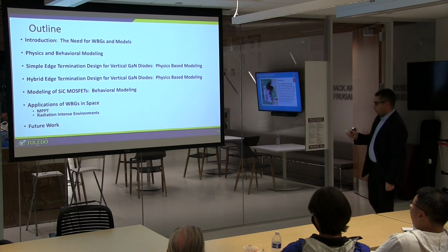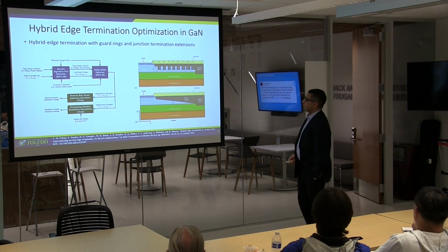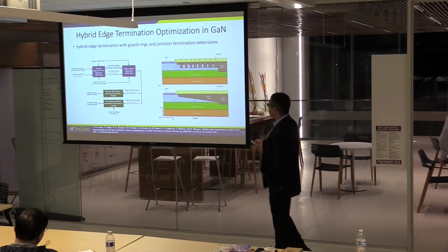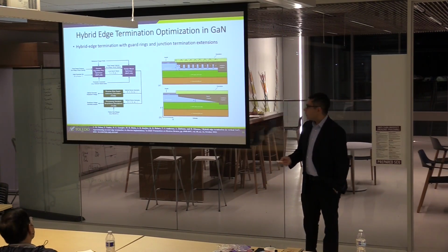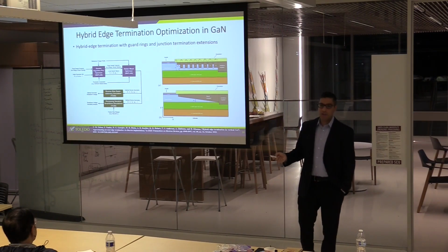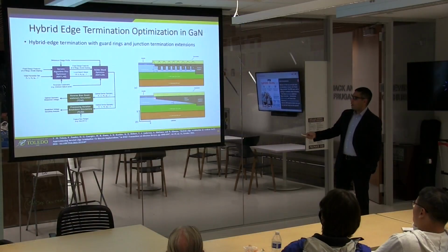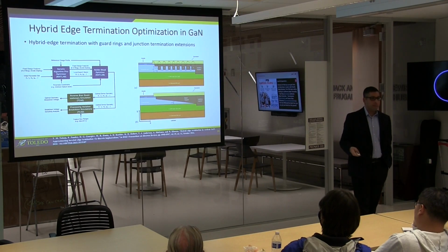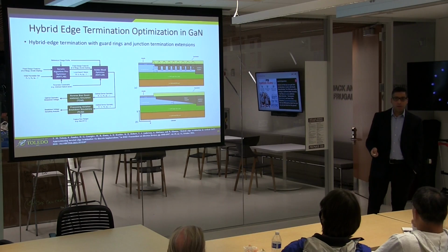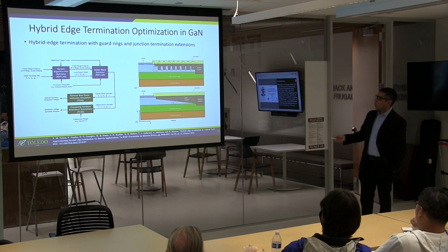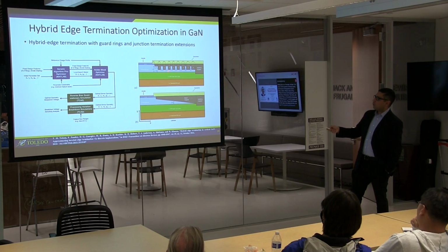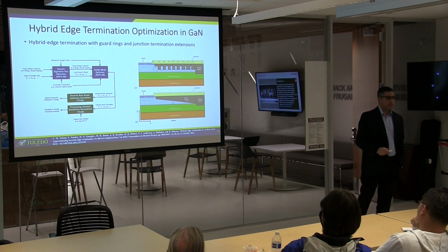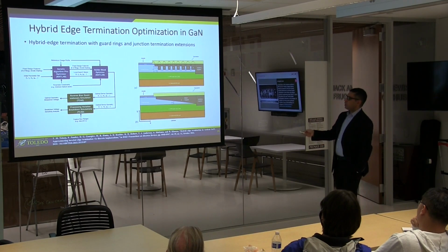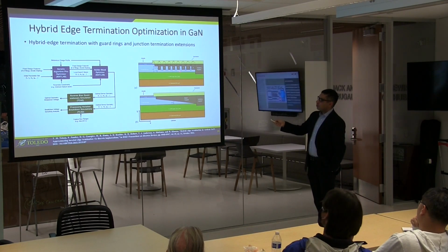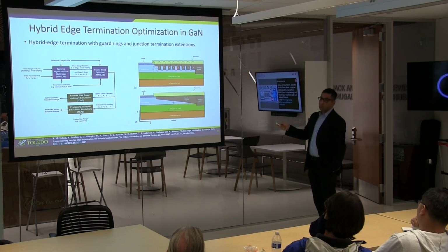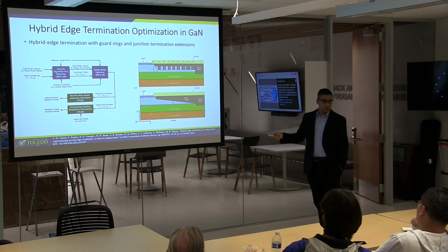So we started to look at hybrid edge termination. Hybrid edge termination is basically reproducing Baliga's bevel here with a combination of guard rings and junction termination extensions. This bevel angle is really, really difficult to fabricate. It's hard to do. But can you basically reproduce this bevel angle with an optimized charge profile that consists of junction termination extensions and guard rings? Basically, we want to reproduce this charge using this structure. This structure, although it may not look like it, is much, much more amenable to fabrication than this structure.